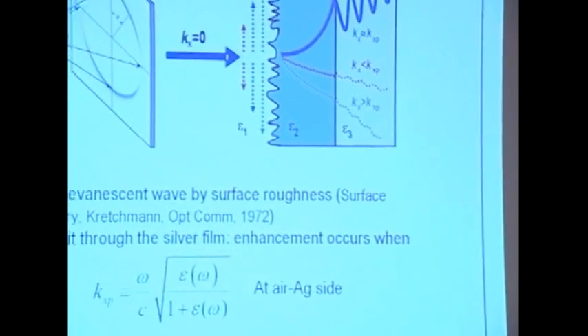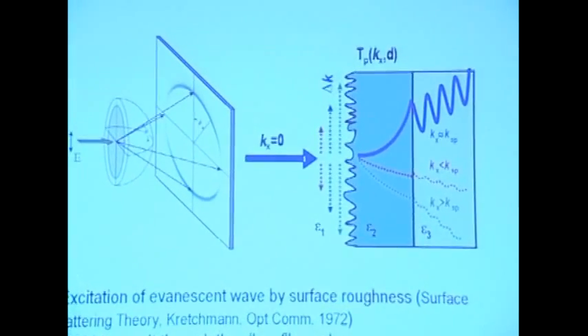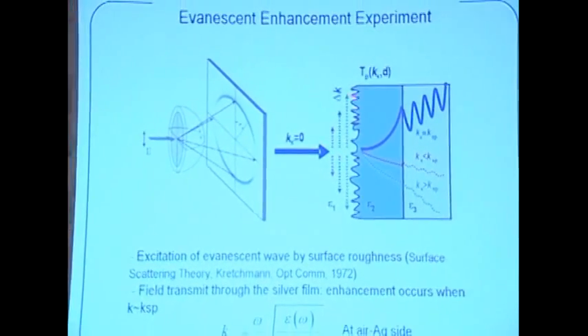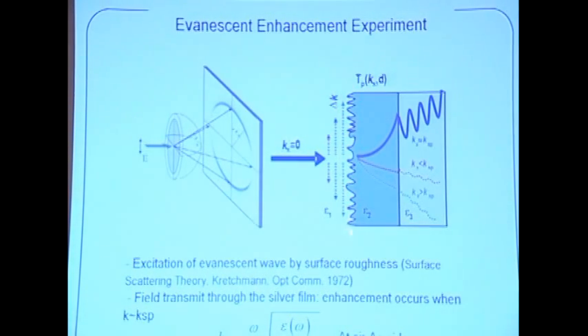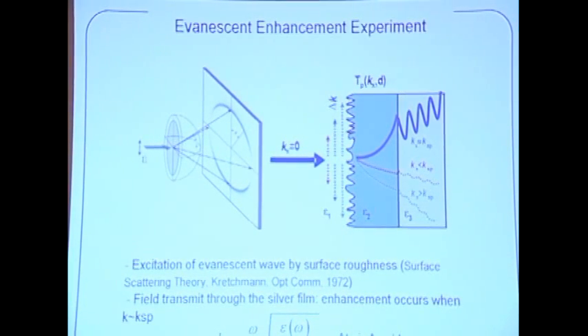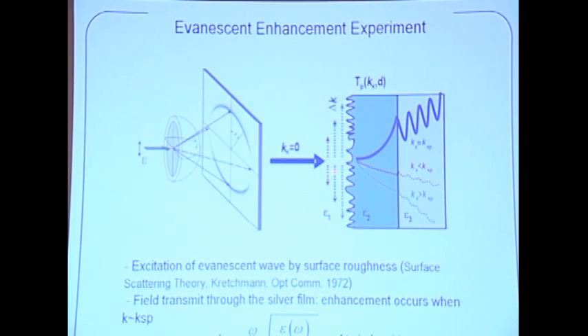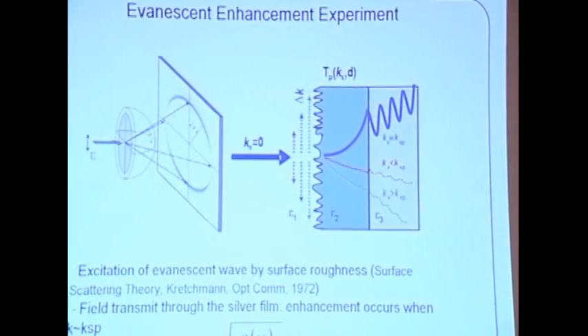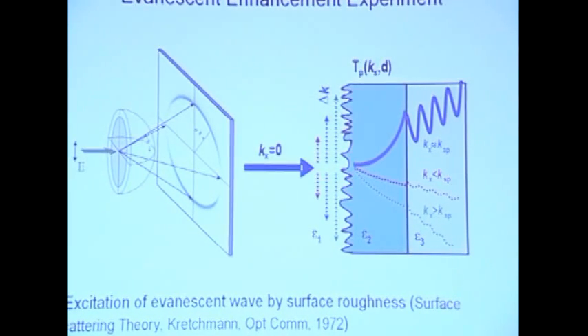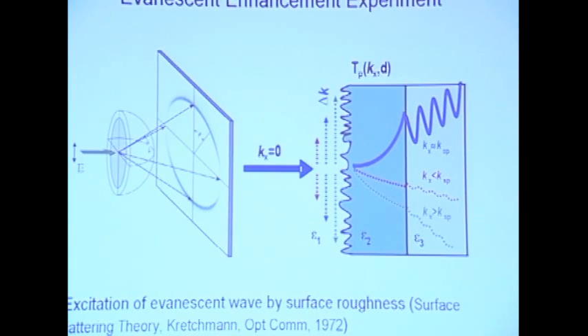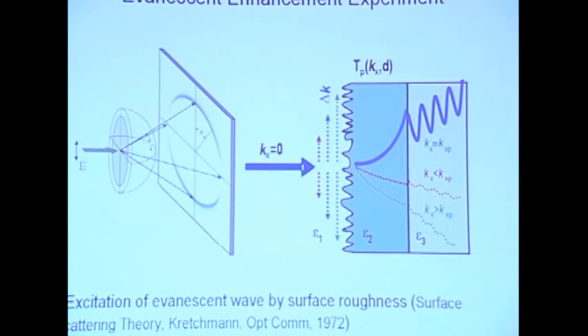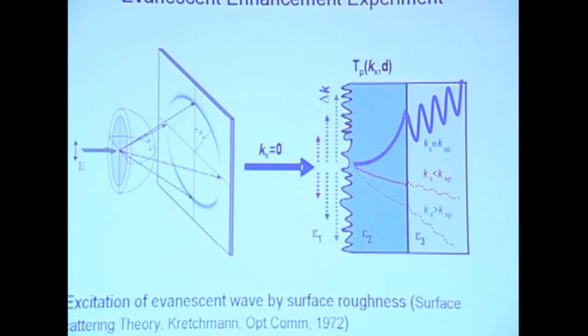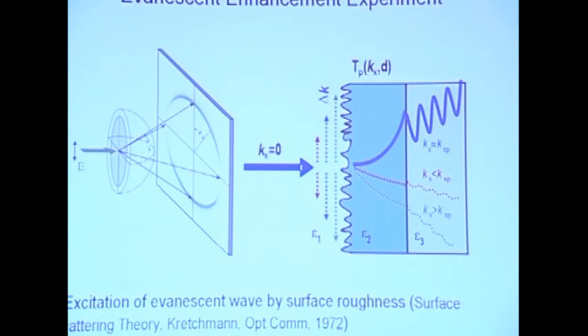So the first experiment designed to test this theory used a piece of silver film and used the surface roughness as a coupler. A laser beam comes in and excites surface waves. Because of the random nature of the surface roughness, that gives you all kinds of k-vectors. So only the k-vector that matches the surface plasmon will be significantly enhanced through this media. And what we want to see is whether this enhancement, this amplitude ratio, grows exponentially with the thickness of the metal film. This is sort of counterintuitive, because usually the field dies out as the thickness of the film increases. But this is actually the key proposition of the theory.